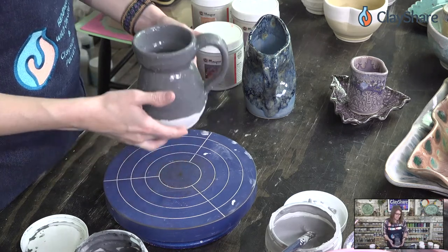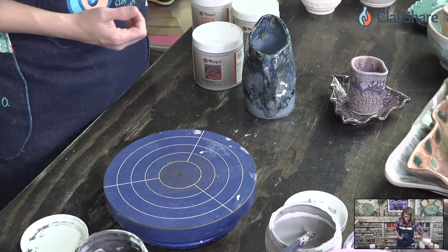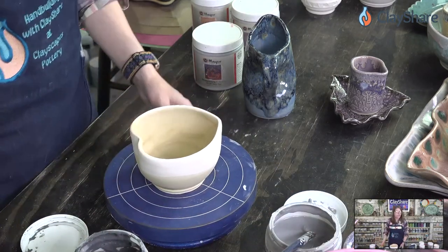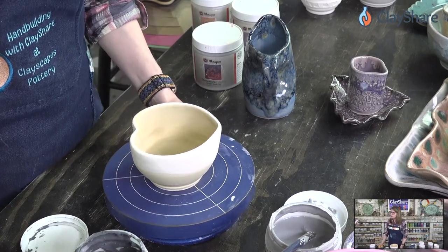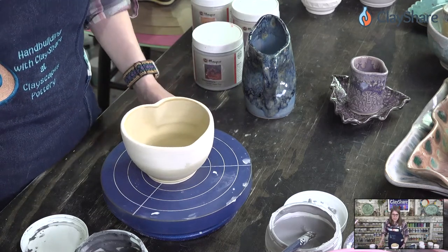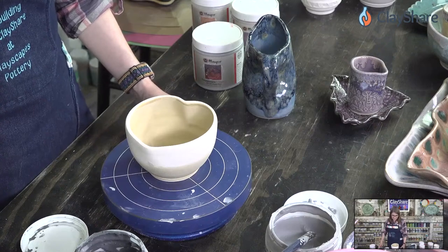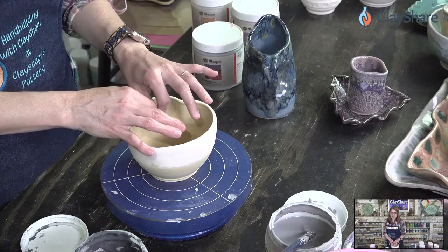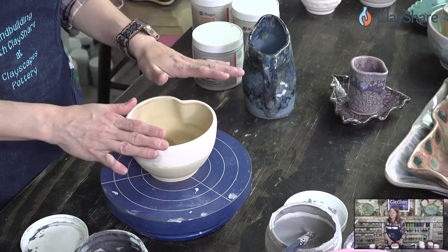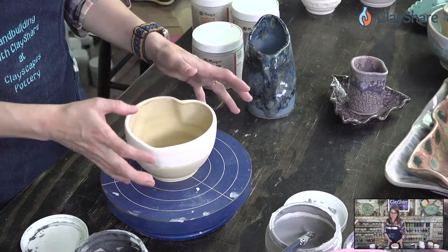What works well over alabaster? Alabaster is a really nice light base color — you can put anything with a lot of movement and crystallization on top. During ClayShare Con, Carmen from Mayco gave some good examples of things with alabaster, and all of ClayShare Con is available for free, so you guys can check that out. When you use a matte on the outside and a gloss inside you can get crazing — you have glazes shrinking at different rates. The only thing you can do is change your clay or use different glazes inside and outside, going with the same gloss on both.